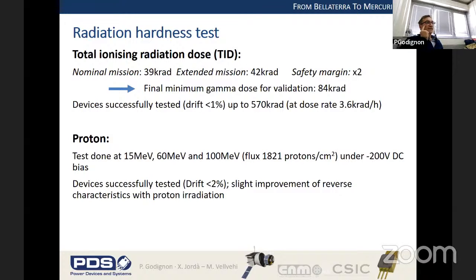So we tested the devices, and we went much above these limits. We tested up to 570 kilorads, and we didn't observe any degradation of our device, confirming in this sense that silicon carbide was optimal for this case. We had pretty similar results with proton irradiation done at different energies and biasing. Again, we had a very small drift of our characteristics, and indeed the drift was in the positive side, meaning that after proton irradiation, the devices were slightly better than before.